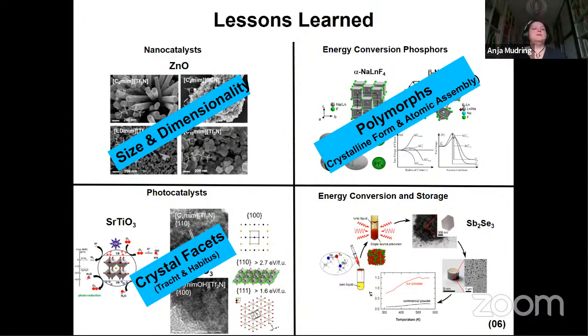And lastly, coming back to the thermoelectrics, so energy conversion and storage, one prerequisite for thermoelectric materials is that you want to have a low thermal conductivity because you want to maintain a temperature gradient, but at the same time, you want to have a high electric conductivity. Unfortunately, the two are related and it's hard to separate them. One concept of separating them is through pores and microstructure. So that is, you take the different scattering lengths of your electrons and the phonons in your material,